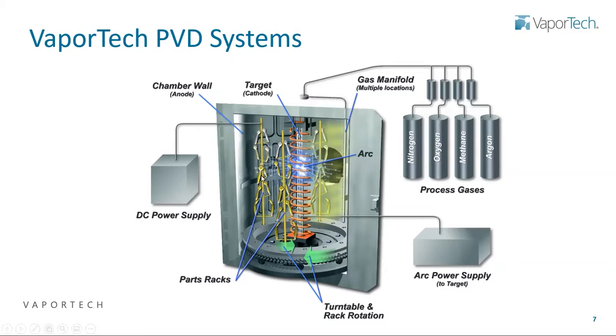Now, on the outside part of the chamber is where you put your parts or your substrates. They're mounted on racks that are mounted onto a carousel, and that carousel rotates around the chamber in one axis, and then each of those racks also rotates on an independent axis for second axis rotation. And this allows for good uniformity of coating coverage on parts as they travel around the circumference of the chamber.